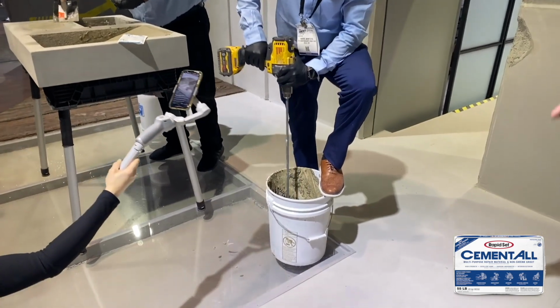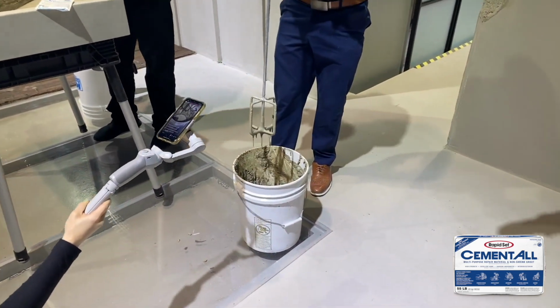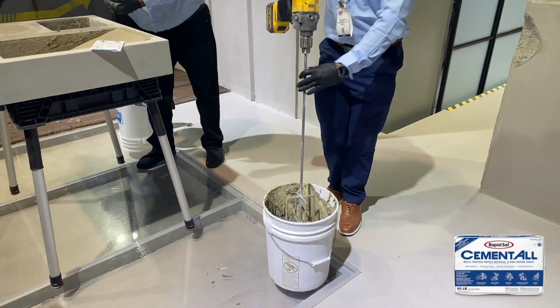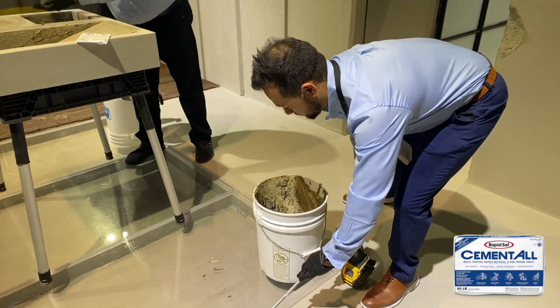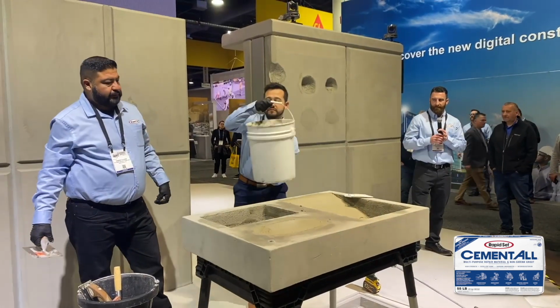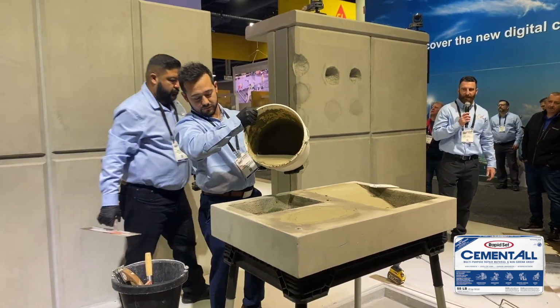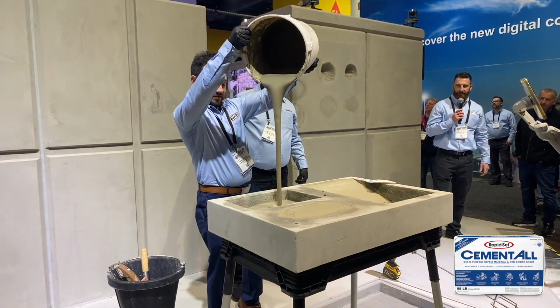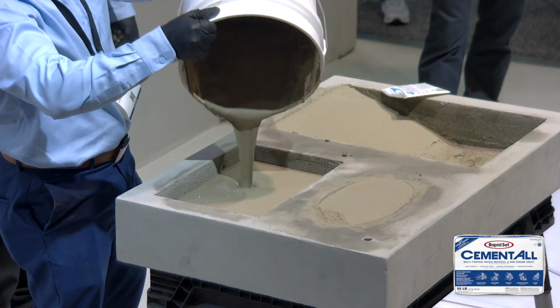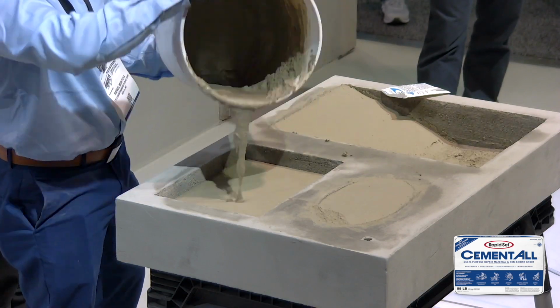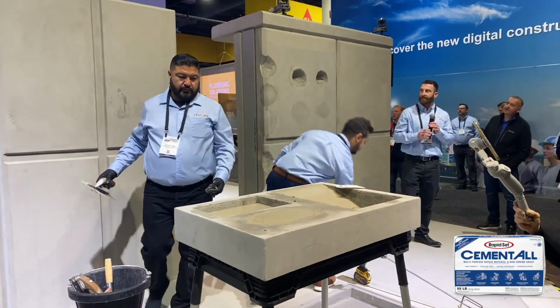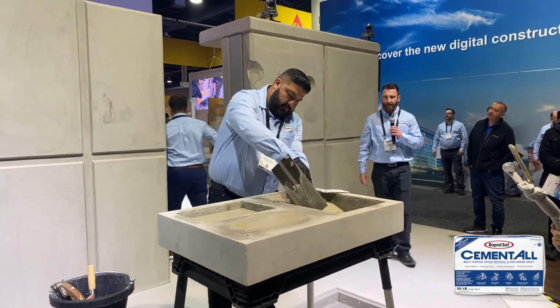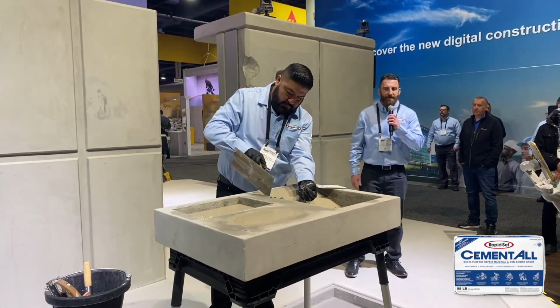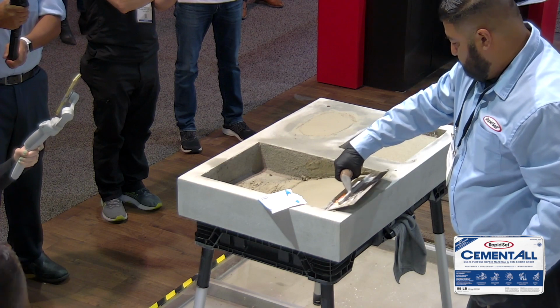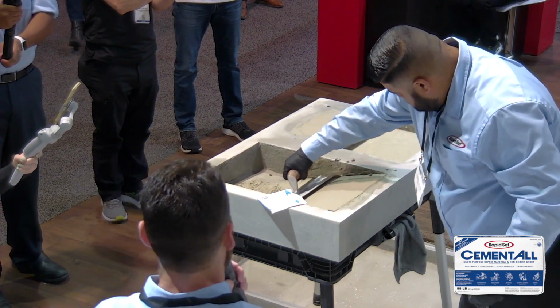Now we can also use this if you don't want it super fluid. We can use the flow control to reduce our mix water, which will give us even higher strengths. So now we can see how easy it is to pour into this hole. So the Cement All will gain structural strength of 3,000 psi in just 1 hour and will actually exceed 9,000 psi in 28 days. So it's a very high strength concrete repair material.